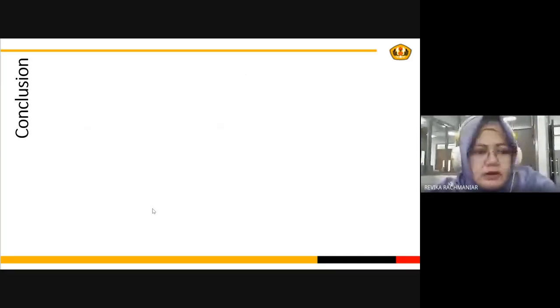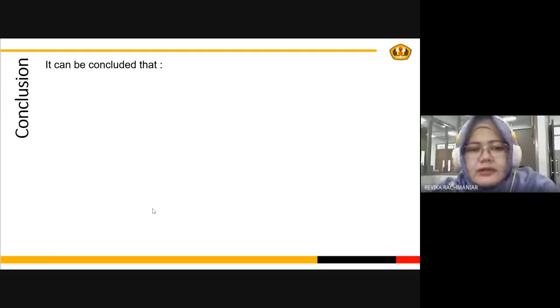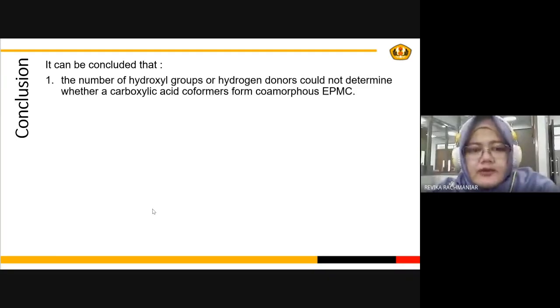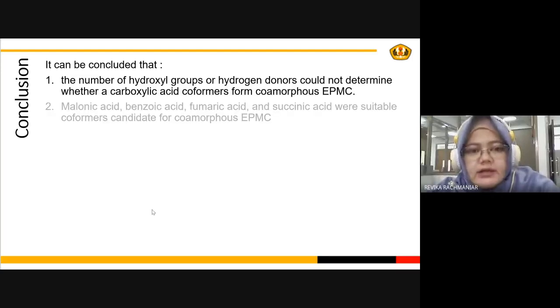In conclusion, it can be concluded that the number of hydroxyl groups or hydrogen donors could not determine whether a carboxylic acid coformer forms a coamorphous EPMC. And second, malonic acid, benzoic acid, fumaric acid, and succinic acid were suitable coformer candidates for coamorphous EPMC.